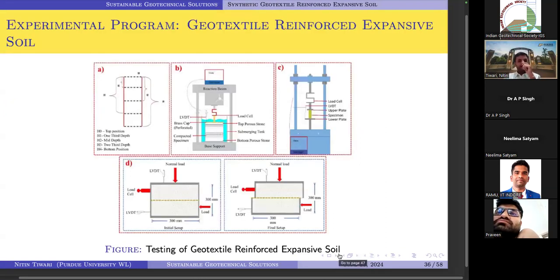So what we did, our target was again the same: how we can reduce the swelling pressure. We used a multiple layer approach. You can see these kind of layers, 1, 2, 3, 4, and 5. We want to see if we place the geotextile layer, geotextile is like a cloth. If you take that cloth and just install it in the field, how will it impact us?